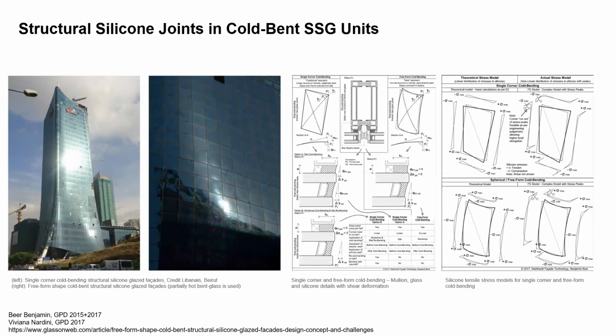geometry here is no longer the glass and what we saw in terms of shape and capacity of the glass manufacturers, but this is the capacity of the secondary seal here, or any structural silicone joint to maintain long-term loading. And these materials are not really good at maintaining long-term shear out there, so they just need to be sized adequately. And so that could be a limitation for the freeform facade that you might want to panel with glass.